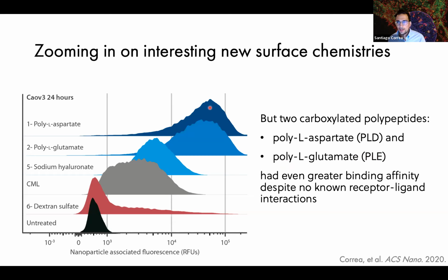And what we can see is that both of these coatings are mediating an order of magnitude improvement in nanoparticle accumulation in these ovarian cancer cells and are outperforming even this sodium hyaluronate system, despite the fact that there is no known receptor-ligand interaction that might be occurring with these polypeptides and the surface of these ovarian cancer cells.